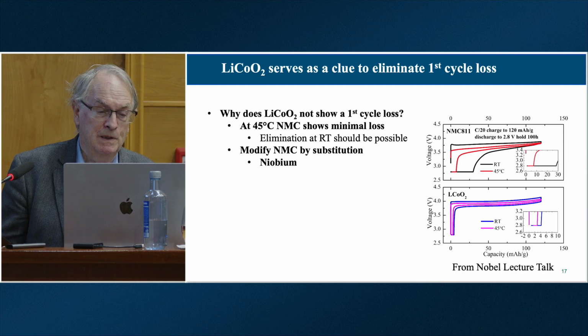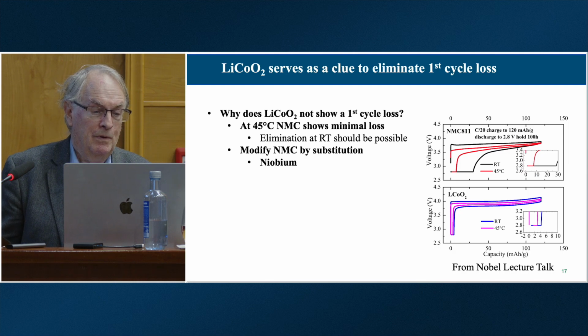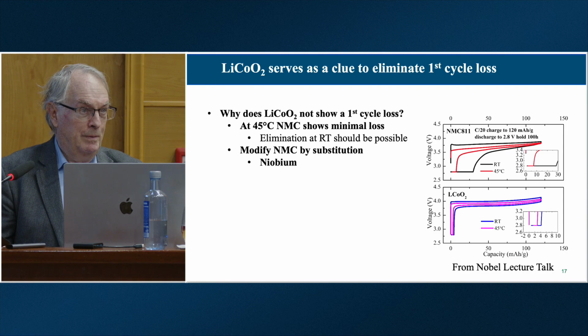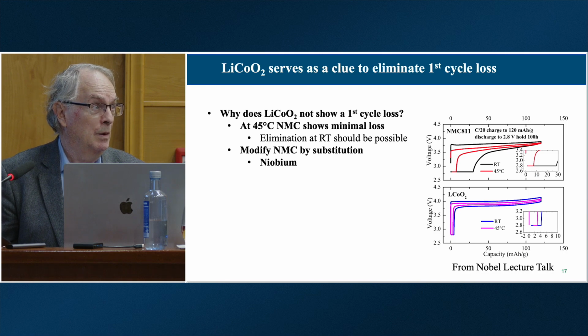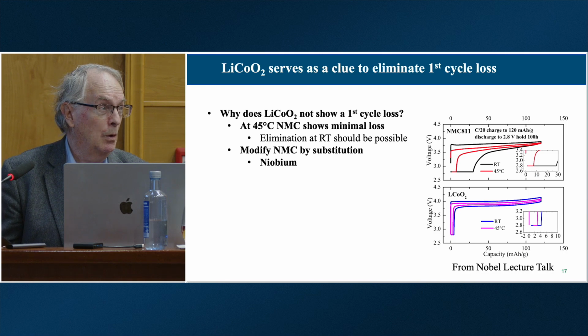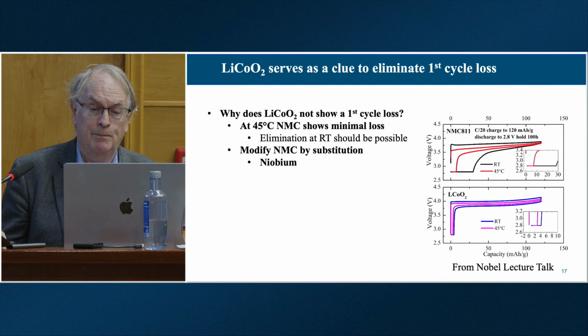The black curve is at room temperature. We've now reduced, when we discharge it to 2.8 volts, we hold it for 100 hours. You can see we get all the lithium back in. At 45 degrees centigrade, it all comes back in. Lithium cobalt oxide, it all comes back in at room temperature. So we've said, let's modify an NMC, and the technique we used was niobium.